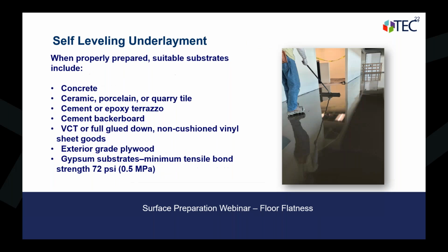Self-leveling underlayments can go over concrete, tile, epoxies, whether it's porous or non-porous substrates. They can go over plywood, they can go over gypsum as long as you have the tensile strength there of 72 psi.